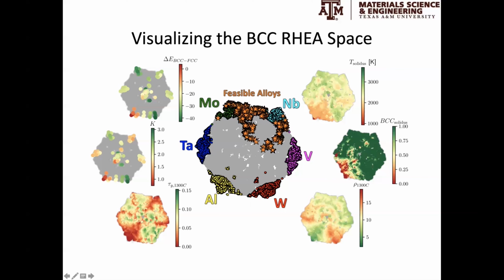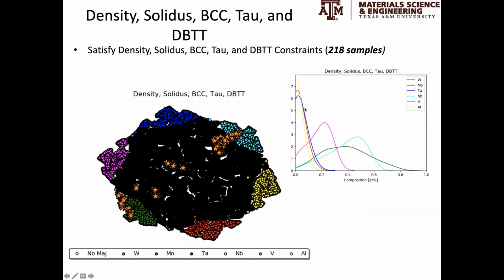If we were to superimpose all these different properties, or performance metrics we're interested in, when you put them together, we find that the feasible space is actually much more reduced, and I will proceed to quantify it in a minute. In fact, when we look at these particular tight constraints, only a very tiny fraction of the potential space tends to be feasible.